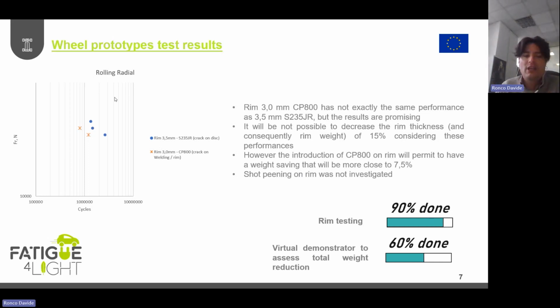One thing that I would like to add is that these tests were done without the shot peening. For the moment, the shot peening on the rim was not investigated. So probably with the shot peening, the performance can increase, and we can reach also for the rim the 15%.